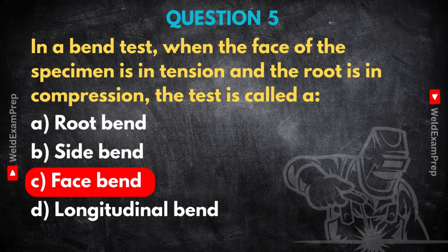Can you maybe walk us through the mechanics? Why is it called a face bend, and what does it actually tell us about the weld's integrity? Sure. If we connect this back to the bigger picture of QA, the naming for a bend test is usually quite direct. It describes what's happening. So in a face bend test, the actual face of the weld, the side that was exposed, the top surface as it was welded, is positioned on the outside curve of the bend. This placement means the weld face gets put under tensile stress. It's being stretched, pulled apart.